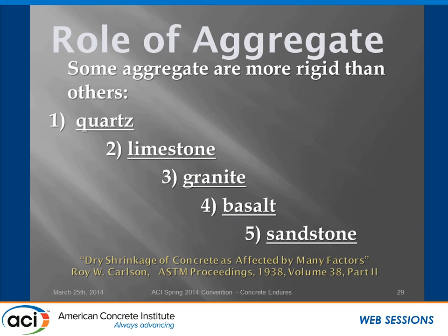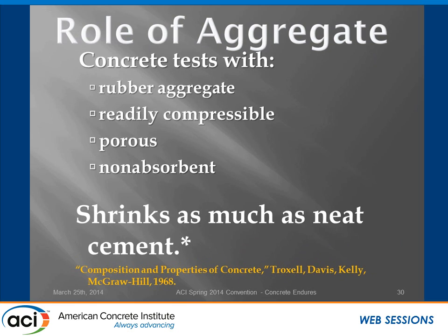Not all aggregates are created equal. You probably know that. This is a list of rank order of aggregate, best to worst. Quartz is known to be the best at restraining paste. It's the most rigid aggregate. And sandstone is the worst in the group. To conceptualize this, if we took aggregate that was very compressible, like a rubber aggregate, and used it instead of rocks, and made concrete out of it, we would find that the concrete shrinks equally to pure paste. So that's a good way to conceptualize what the rocks are doing in there for us.